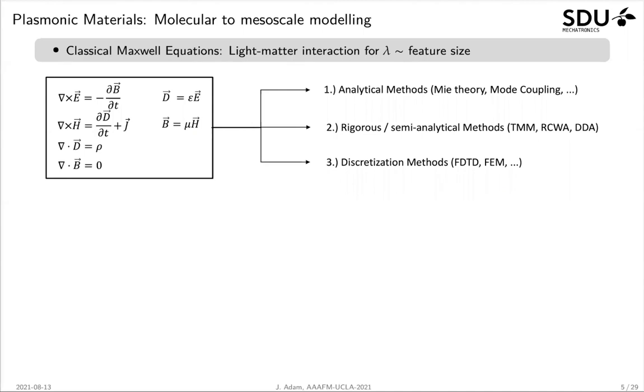So how do we model plasmonic materials? We propose a combined molecular to mesoscale modeling approach where we can tackle the structures built of material by classical Maxwell's equations — so light-matter interaction in the feature size of our wavelength. We are free to tackle them with either analytical methods for high-symmetry situations, rigorous or semi-analytical methods for one- or two-dimensional structures, and discretization methods like FDTD or FEM for more complicated structures.